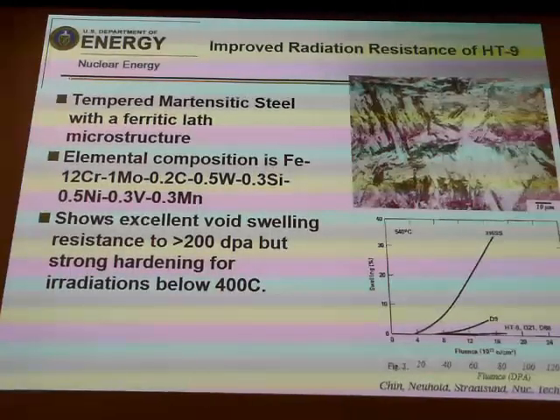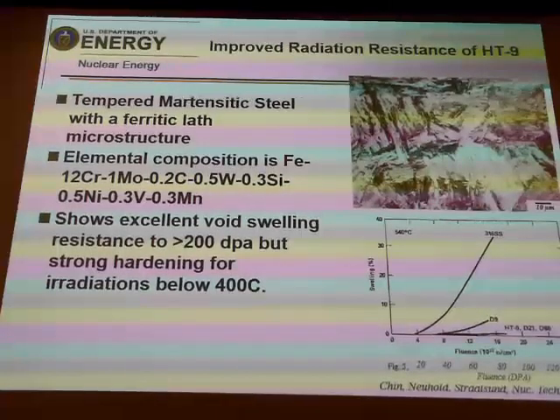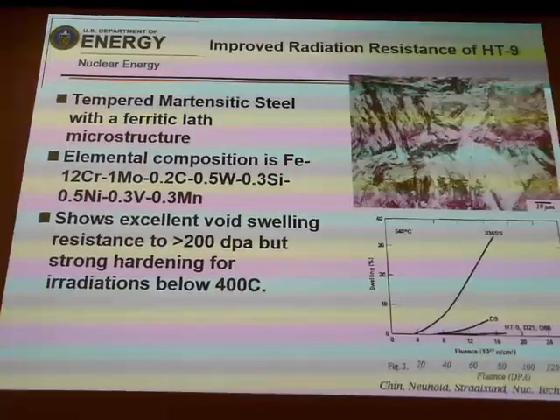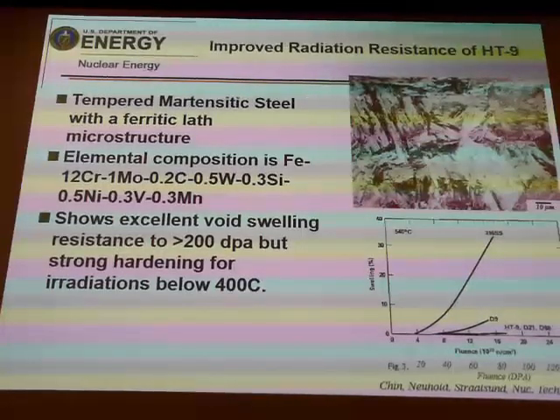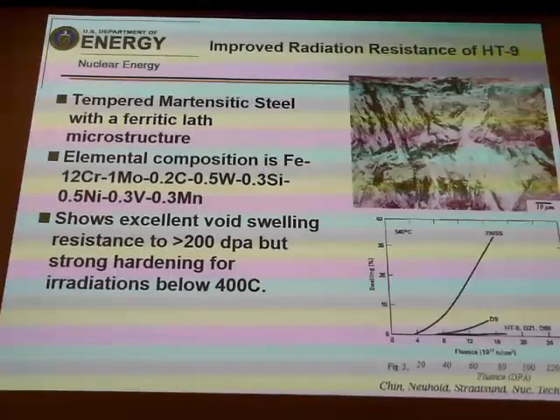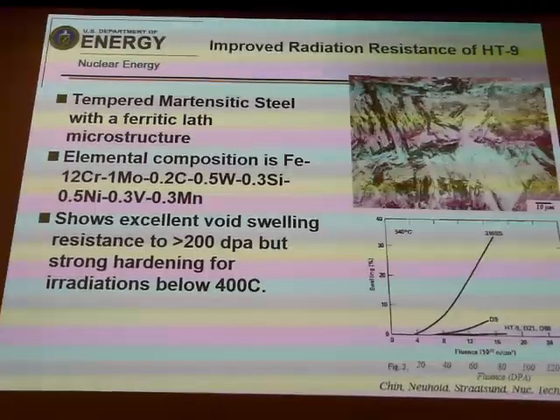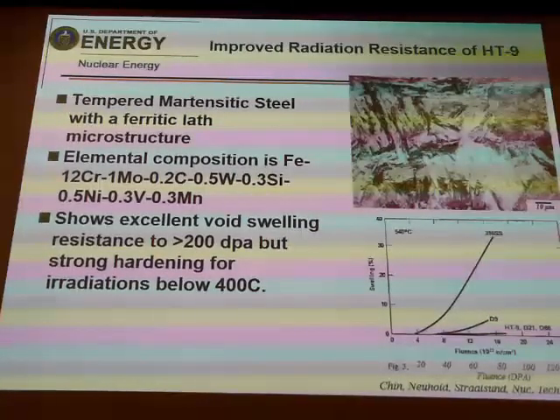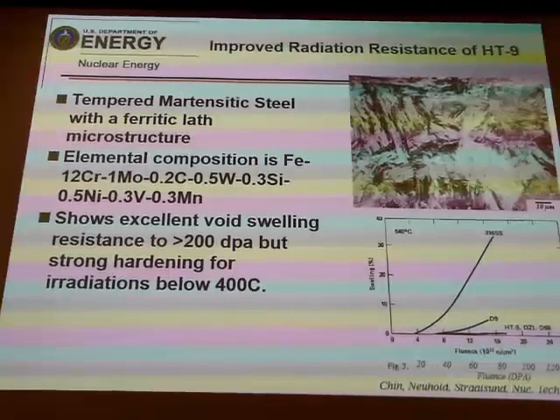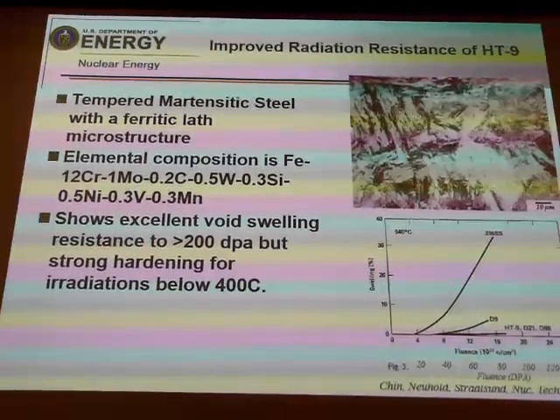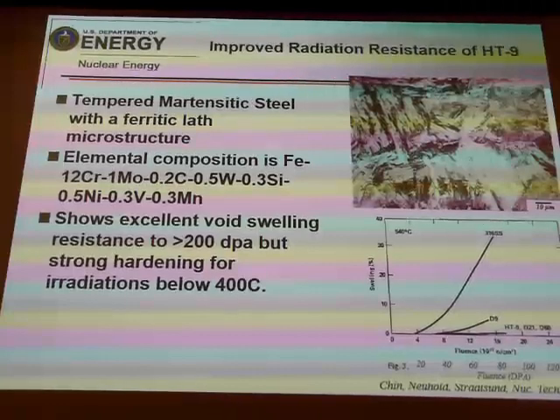And this has been known for a while. This article back in '82 noted the difference between an austenitic stainless steel like 316, another austenitic stainless steel D9 that has titanium additions to it, and then HT9 and some other variants, which showed significantly reduced void swelling. This is fluence, but down here you can see the translated DPA. It's about 80 DPA. You can see that we're at 5% swelling in a D9, or even almost 30% in 316, but HT9 is very little.